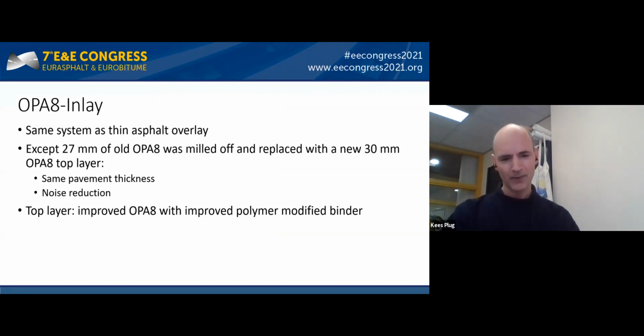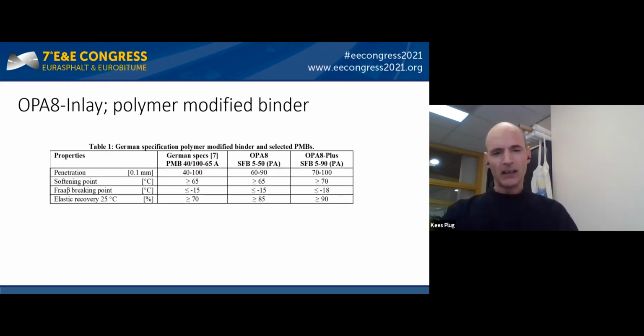The OPA inlay has the same principle as the overlay. Only now 27 millimeters of the old surface is milled off and replaced with a new layer. So there's no height difference between lanes. The top layer has been improved further with a heavily polymer modified binder compared to the original OPA 8. As OPA 8 inlay polymer modified binder, this is a special, heavily modified PMB. For the standard OPA, a standard polymer modified binder was used. Both binders exceed, however, the German specification for the PMB 40-100.